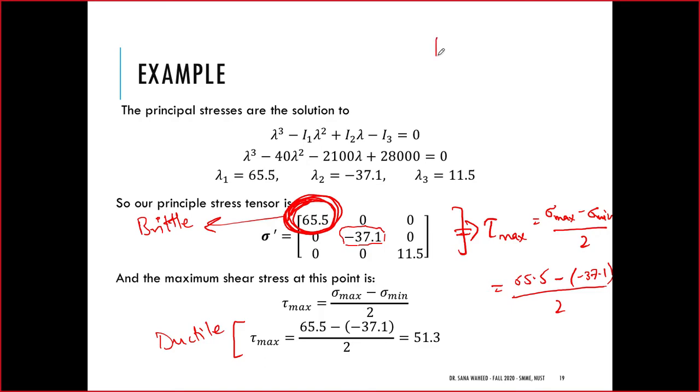क्योंकि उन्हीं से, let's assume कि कोई brittle material में crack है, तो जब वो खिंचेगा, right, जब उसमें tension होगी ना उस crack के ऊपर, तो फिर ही वो propagate कर जाएगा through and it will cause failure. Whereas if you have normal stresses which are compressive, which are closing this, फिर तो वो crack बंद हो जाएगा ना, तो फिर तो actually आसान हो गया काम. So be careful here as well, that just for your information, okay, it's the tensile stresses which are important for brittle materials. Perfect.